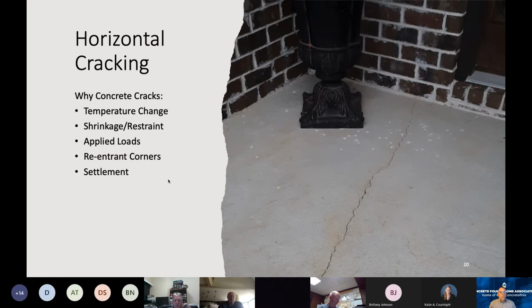So here's a porch stoop slab. And in this particular design, you might expect a frost wall around the perimeter of this slab, and then they poured a concrete cap after they backfilled it, and let's hope that they engineered it and put a nice subgrade aggregate underneath there. And then they placed this concrete and really felt like they did a great job. It was a beautiful looking surface that they left for the homeowner. And the next winter, actually coming out of the winter, the next spring, they get a call from the homeowner saying, I've got this huge crack across this porch stoop. What caused it? What are you going to do about it?